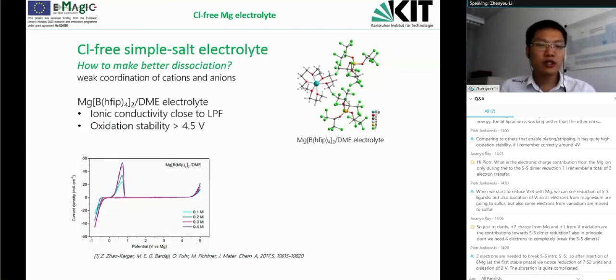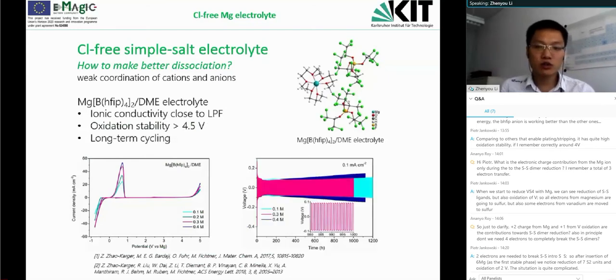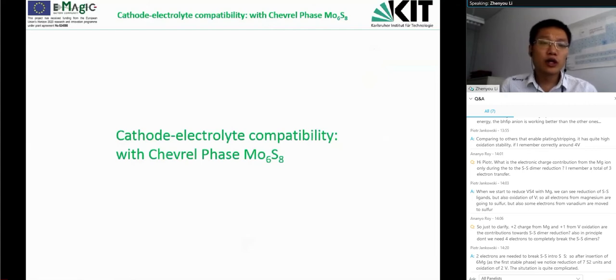So from the CV, we see we have even higher oxidation stability of up to 4.5 volts against platinum, and we have very efficient magnesium stripping and plating as shown in the reduction and oxidation peaks. So the long-term cycling is also good. In a symmetric cell, we could run it for more than 1,000 cycles, and we didn't observe an obvious increase of this plating stripping overpotentials. So with a nice electrolyte solution, we move one step forward.